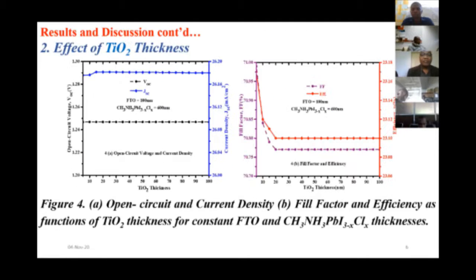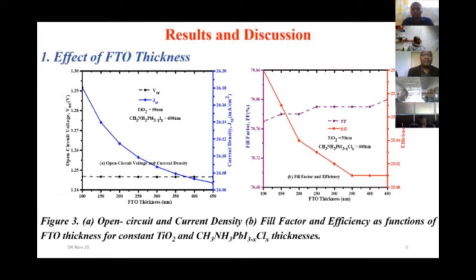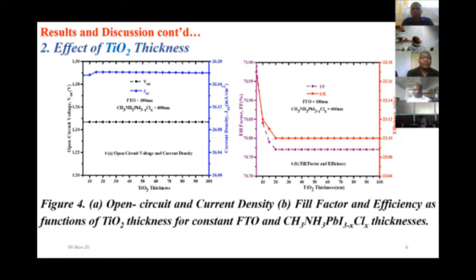So our major aim was to find the optimum film thicknesses, and from our study we concluded that for FTO, 100 nanometers could give us better performance of the cell, as evidenced from these results. We also discovered that variation of the TiO2 thickness does not alter the cell performance much, but a TiO2 film thickness from 5 nanometers to about 100 gave us significant results.